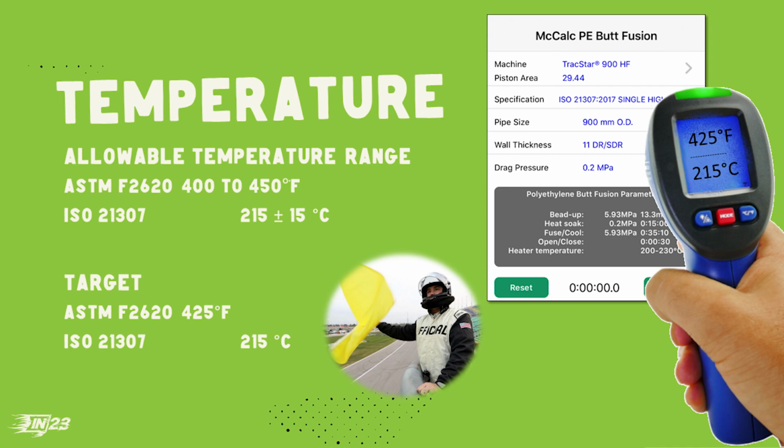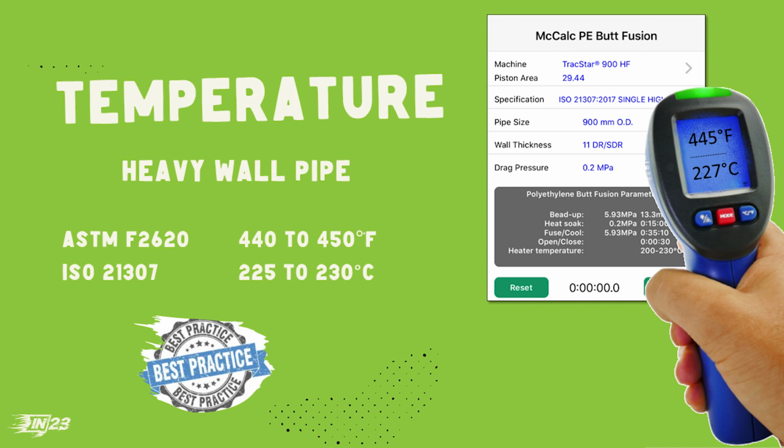Mike and I were talking about that yesterday, and he asked, why do you do that? Think about a pipe wall; I saw some yesterday that are 4 or 5 inch thick walls. That's a lot of mass. You put your heater up against that, and it's going to suck the heat right out of it. If you're running at the higher temp range, you don't have to worry about it dropping below where you need to be.